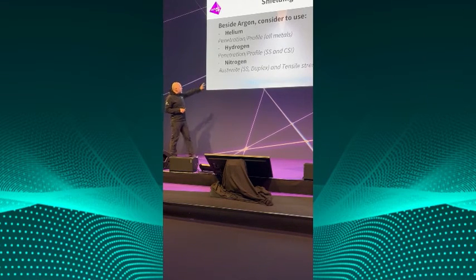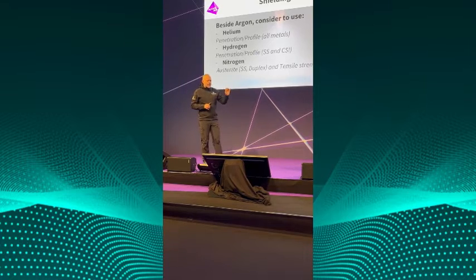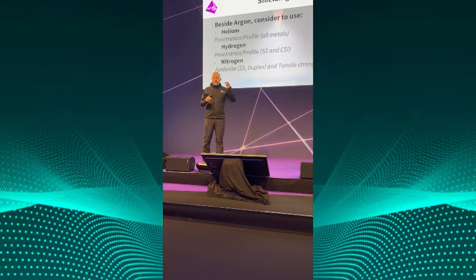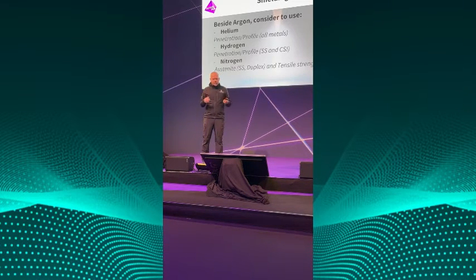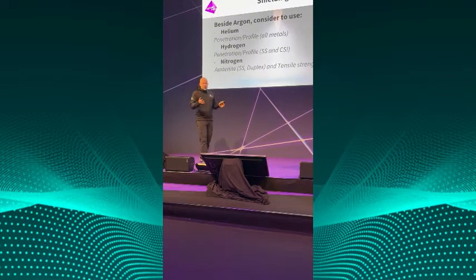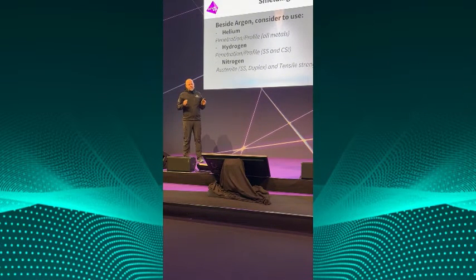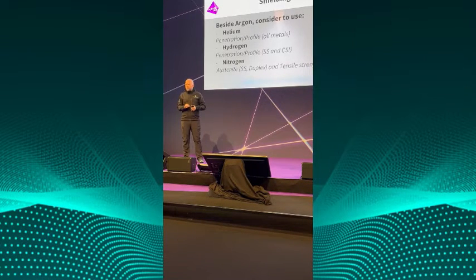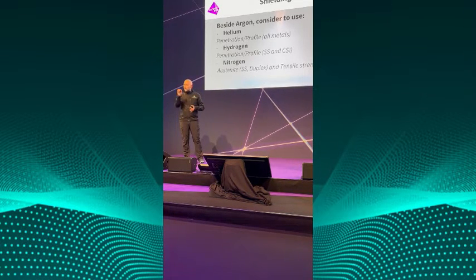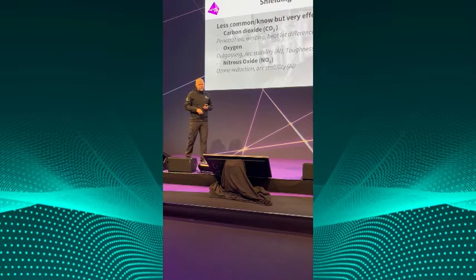When welding duplex steels or stainless steel, you can adjust by adding nitrogen the proportion of austenite and ferrite, or reduce unwanted components such as delta ferrite. And probably something new, you can also increase the tensile strength in stainless steel without causing embrittlement, and not by like 2-3%, by like 15%, which is kind of unheard of. By adding a gas, you increase the tensile strength.